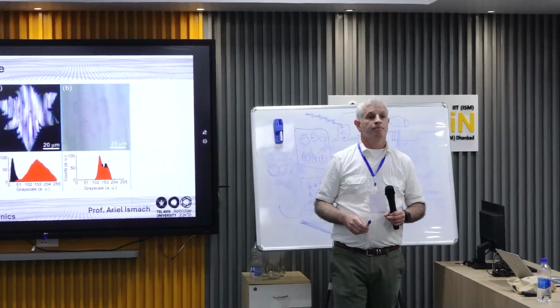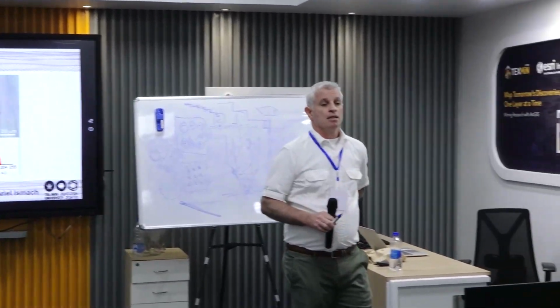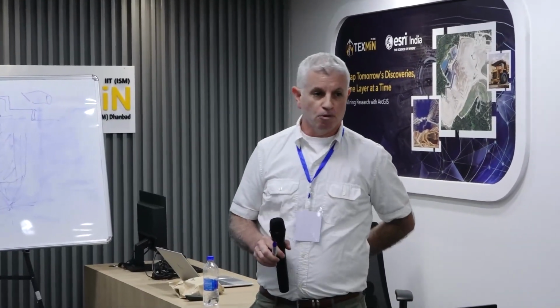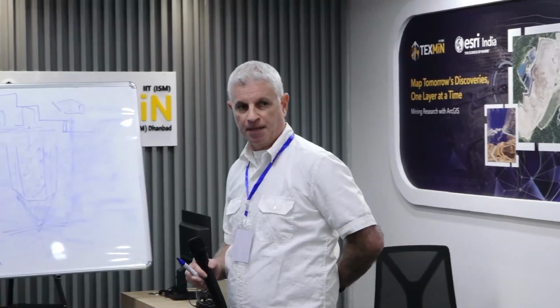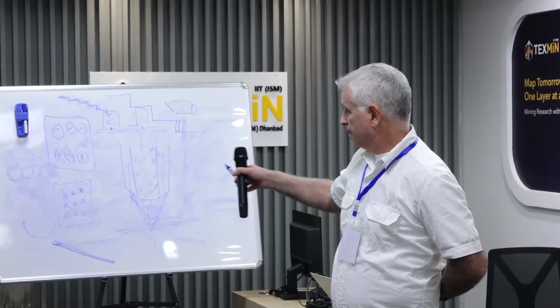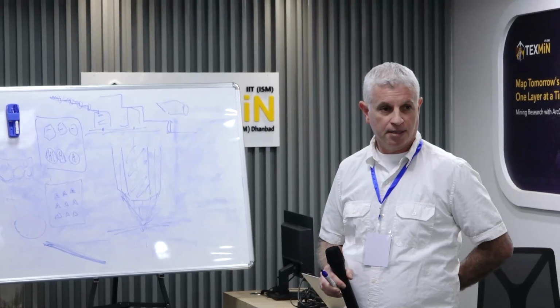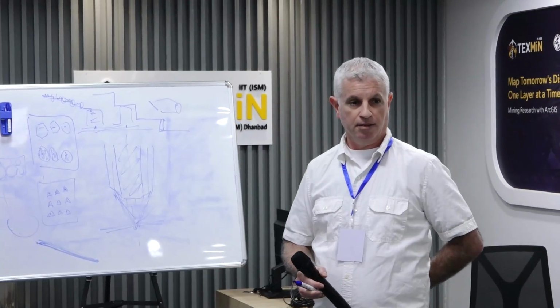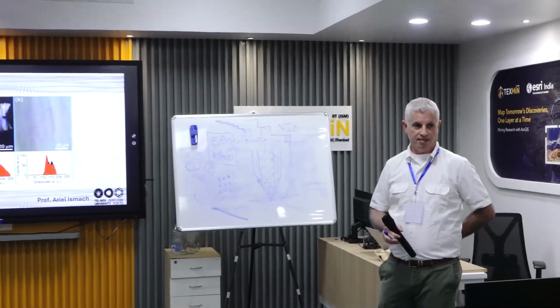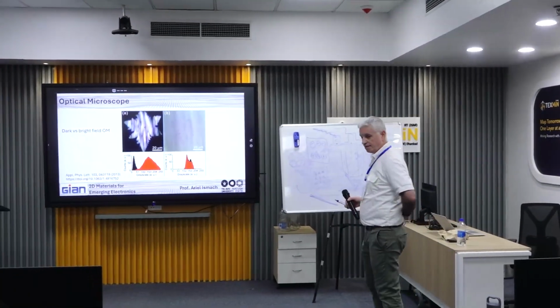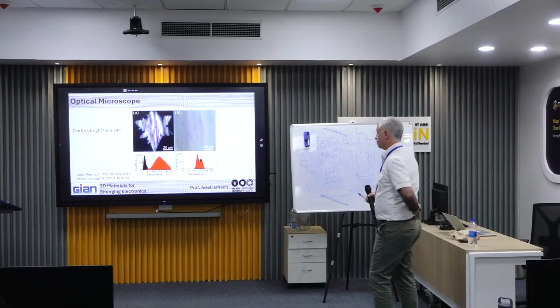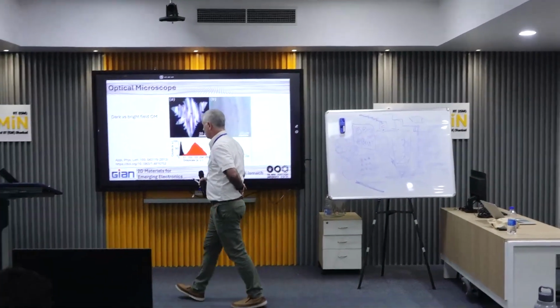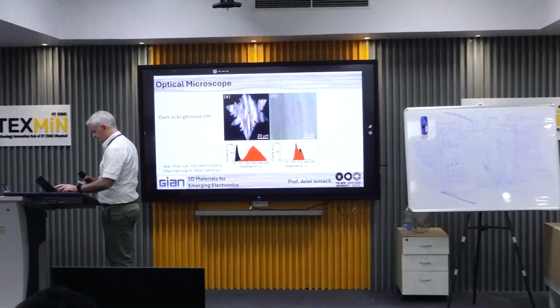So what is the typical step size? Typical size could be sub-nanometer to a few nanometers usually. Some of them you don't pick up. The sub-nanometer is very hard to pick up. I don't think that you pick it up. But in the rest of the polycrystalline material, you will find a lot of places with the nanofacets. So if you see the nanofacets, you know that you have graphene. This is another indirect way to check for graphene.